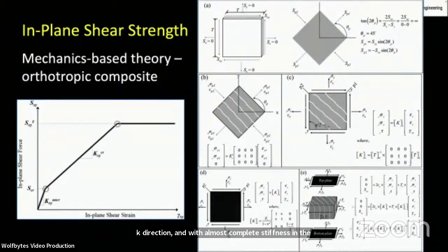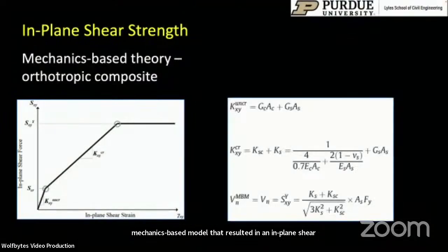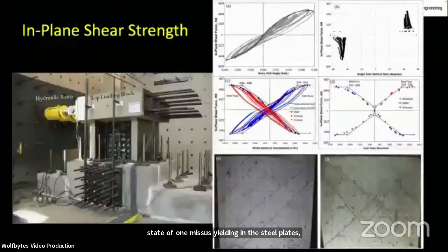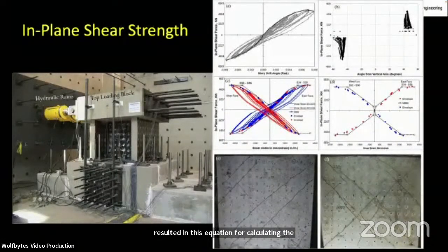We were able to put all of this together into a simple mechanics-based model that resulted in an in-plane shear trilinear curve that explains the in-plane shear behavior of this system, which provided equations for that stiffness for the composite section before cracking, stiffness after cracking, and the in-plane shear strength, which corresponds to the limit state of von Mises yielding in the steel plates, resulted in this equation for calculating the in-plane shear strength. This equation was verified through large-scale testing that was done in our laboratory.